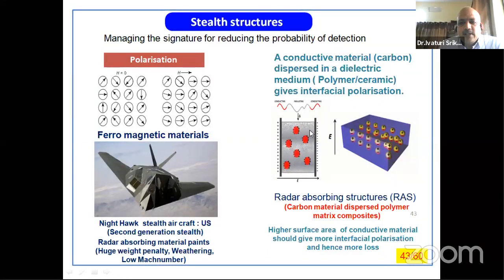Now, new generation aircrafts are using carbon materials. Carbon is a conductor. If you disperse them in a glass epoxy, GFRP, in one of my first slides I have shown CFRP and GFRP are the two major classes. If you take GFRP, add carbon materials, and expose this system to a microwave field, there is a polarity between the carbon and the dielectric medium. And again, these polar molecules will try to flip-flop with the propagating wave.